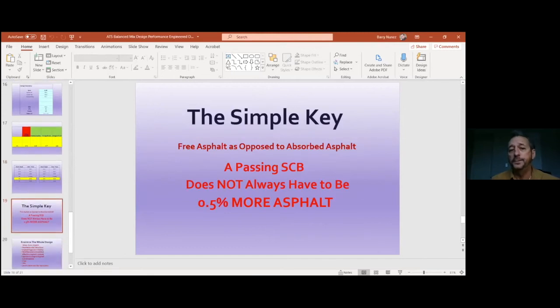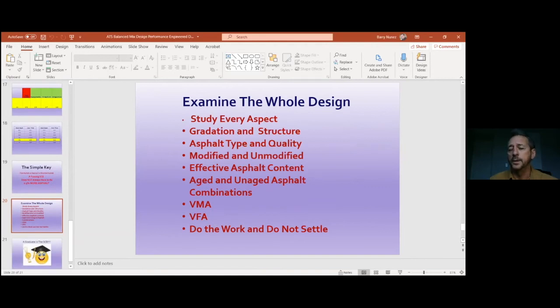So the simple key, free asphalt as opposed to absorbed asphalt, is a very big key here to make an SCB that's borderline or failing move up the ladder. So it doesn't always have to be a 0.5% more asphalt. Now, I understand if you've got a mix design and you're doing this in other states, you might just take that mix design and run the 2 tests, and if it shows 0.3 more or 0.4 more or 0.5 more, maybe that's what the state wants you to do. But as most contractors, we're in a low bid world, so we've got to be true designers, manipulate those gradations, work with that dust, and I think you'll get some very good results without increasing the mix cost a lot.